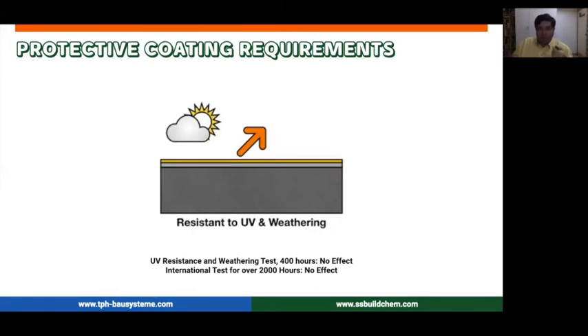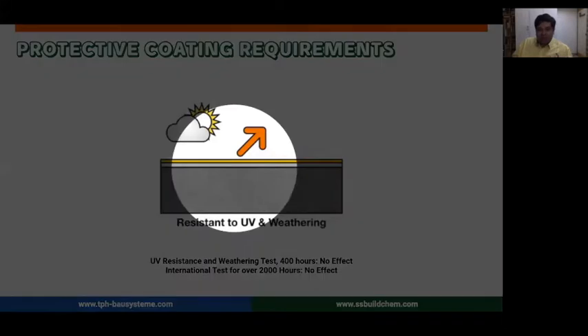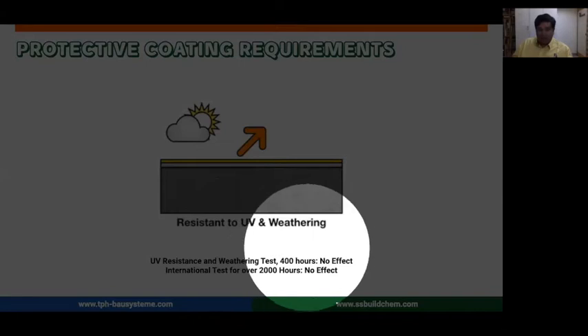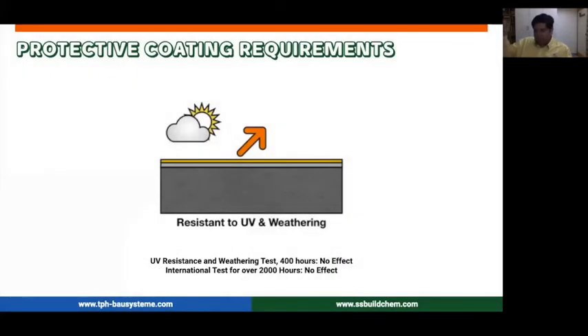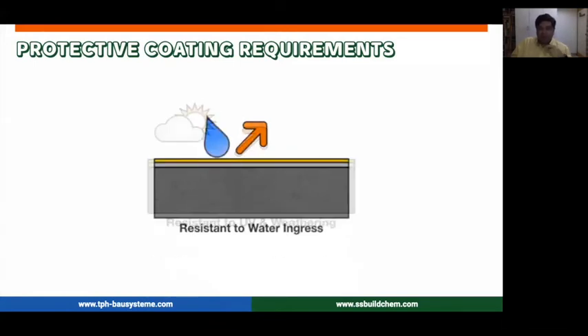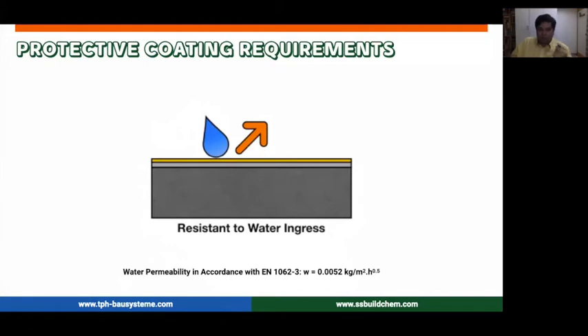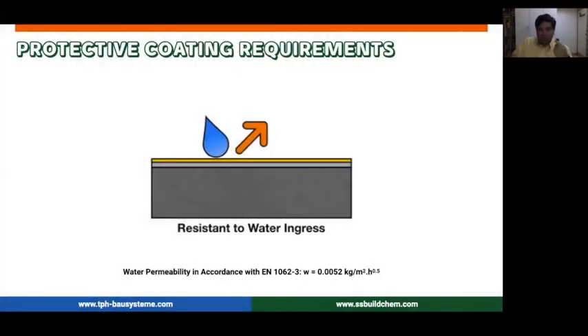The next requirement, of course, is that it should be resistant to UV and weathering. Normally this is tested by ASTM G53, where the coating is kept under UV light for about 400 hours to almost 2000 hours, and then they see what the effect is on the coating. Of course, your coating has to be resistant to water ingress. So it's tested for water permeability in accordance with EN 1062. That should be very, very low, less than 0.1. If not, your coating is going to let water go through.